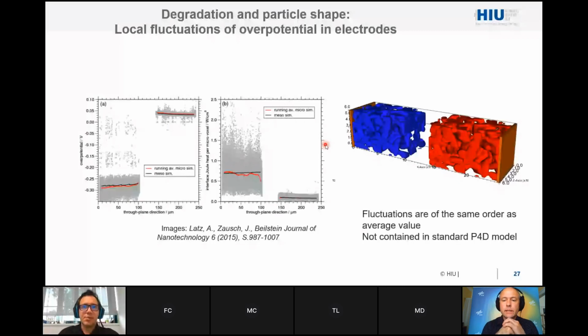So for the last seven minutes, I want to share with you some new results based on some older simulation which we did in 2015, and I want to explain this slowly. So what we did was the following: we created an artificial geometry, Jochen Sarge and me, and then we did at that time a thermal simulation. Therefore, you see here the overpotential, and here the production of Joule heat at the interfaces due to intercalation and deintercalation.